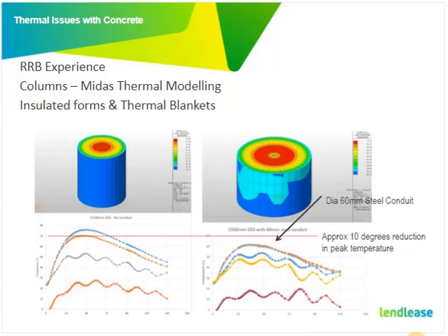So, in the columns, one of the things that we did during the design was insert a steel column into the centre, basically just a 60mm conduit into the centre. It's hard to tell from this graph, but basically what that did was change the peak temperature location to be not at the centre, but a third of the way from the centre to the surface.